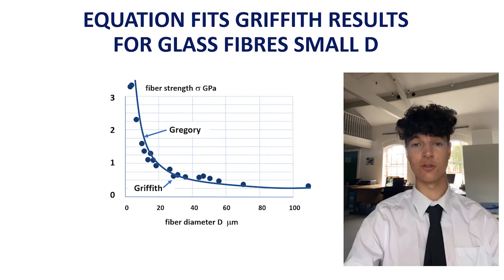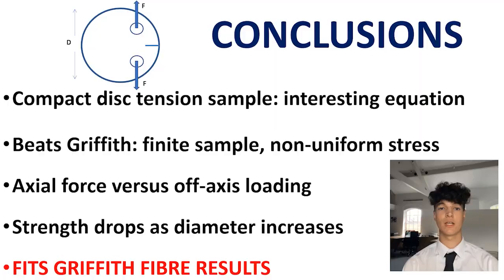Moreover, the Gregory curve fits Griffith's original results on strength of fine glass fibres. Griffith, in 1920, melted glass and pulled it to form fine fibres of several diameters. He got results showing fine fibres were stronger, but could not explain it with his cracking equation on infinite sheets under uniform tension. In conclusion, these calculations show that Gregory's equation is more interesting than previously thought.